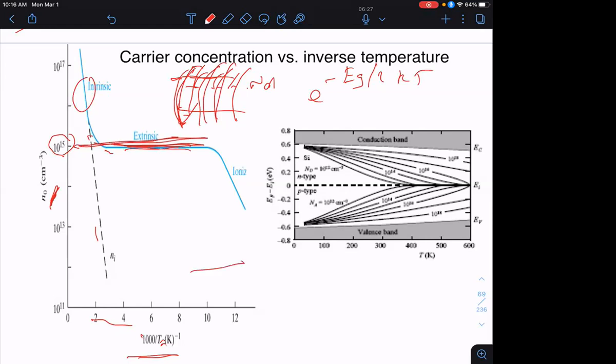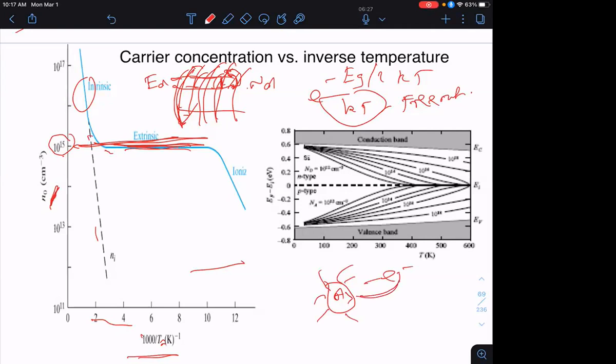Conversely, if I go to very, very low temperatures, even though this separation of the donor level is very, very small, if kT is made smaller and smaller and smaller, these carriers created by the donor fall back into the donor level. That's called carrier freeze out. So you're freezing out these conduction electrons back into the donor level, okay? In other words, if I have an arsenic impurity, donor impurity, normally the 5th electron would have been donated to the crystal, but now at low energies, it gets bound back into the arsenic atom itself. The carrier gets frozen out.